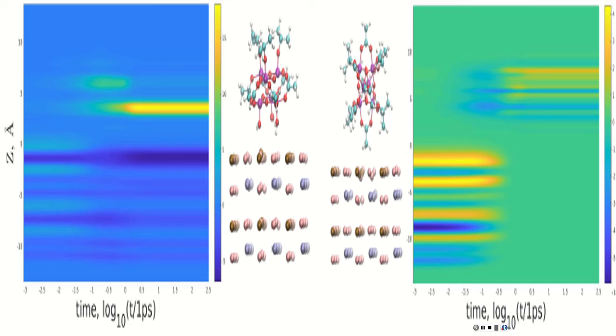So, in the case of the acetic acid, the original excitation always goes to perovskite. So you see this alternating blue and orange, which means the initial excitation stays on perovskite. Orange means lead 5s orbital, and blue would be bromine p, whatever is available there. And as time passes by, both electron and hole don't migrate to titanium dioxide. So there is no charge transfer. Well, there is one very short